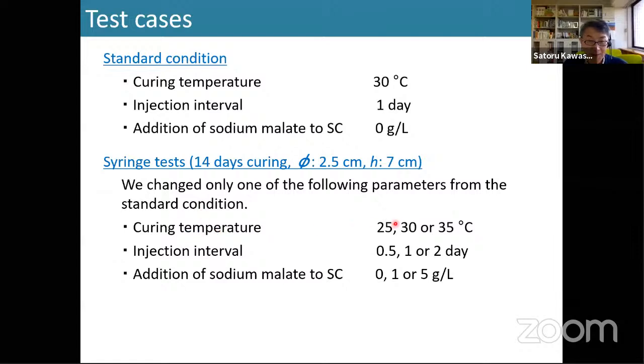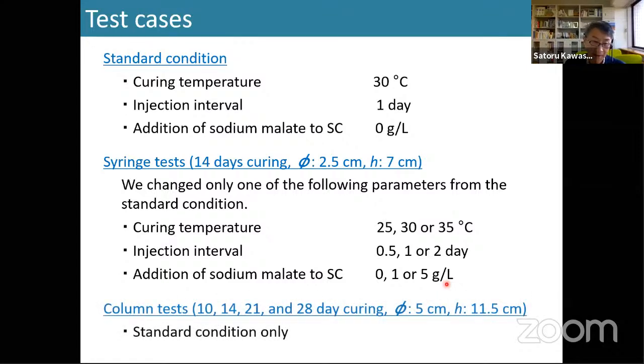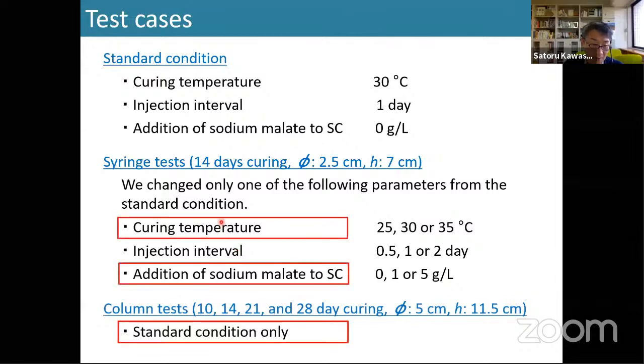The curing temperature we varied, not only 30 degrees Celsius, but also 25 and 35. The injection interval also, not only 1 day, but also 0.5 and 2 days. And adding organic matter, not only 0, but 1 and 5 grams per liter. And we also conducted a larger size: this one is 2.5 centimeters, the other one is 5 centimeters, 2 times larger than the syringe. We just call it the column test. Today we just show these red squared results.